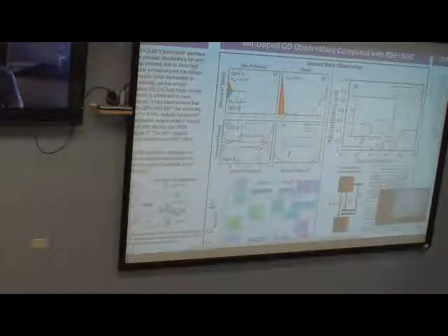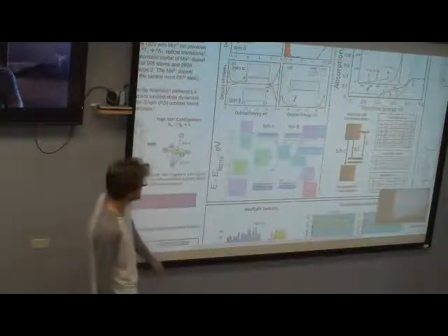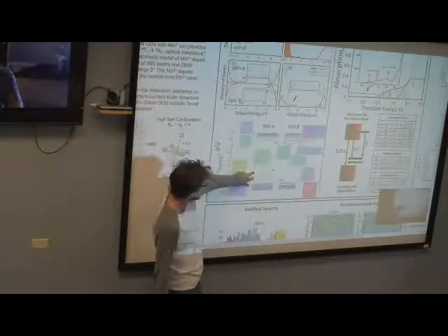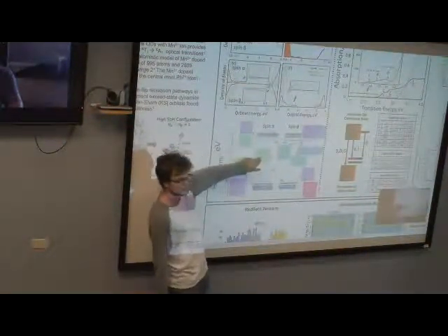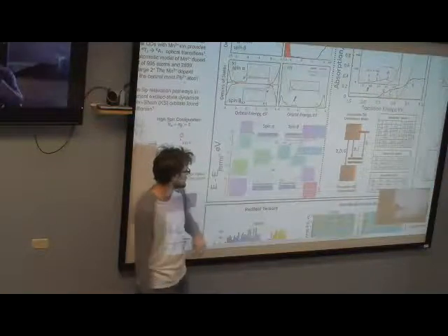And below that is just some pretty orbital plots to go along with the spin polarized density of states. So for the states that are within the gap, you can see that those are D orbitals. This is some sort of DXY hybridized with the P orbitals around it. And this is a DZ squared orbital that hybridized a little bit with the surrounding ligand field.